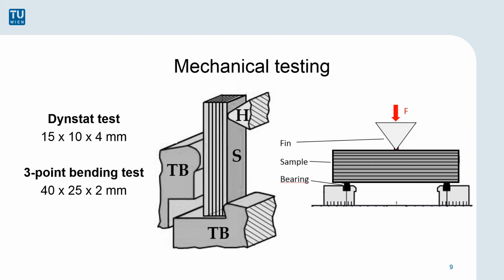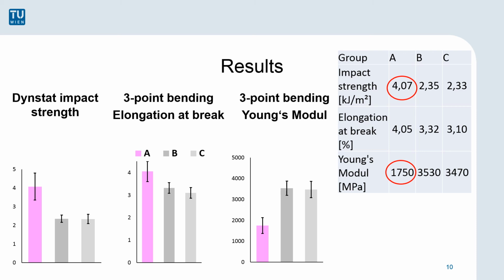Additionally, 3-point bending tests are conducted to gain insight into how other mechanical properties, mainly Young's modulus and bending strength, are influenced by the compliant material layers. The results of both Dynstat impact strength tests and 3-point bending tests show promising results. The impact strength of samples produced with the bio-inspired approach of alternating material layers displays a significantly higher value compared to the other two groups.